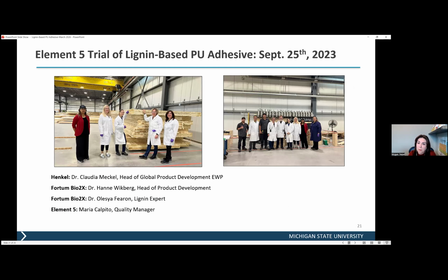We also did a manufacturing trial at the Element 5 site in collaboration with Henkel. We went there and made larger scale glulam samples. After the samples were pressed, they cut the samples in half, sent half to Henkel and half to MSU. We tested all those samples prepared for delamination. Even though none of us applying the adhesives were experts in adhesive application, the glulam samples that we made passed the delamination and other tests that we've done.